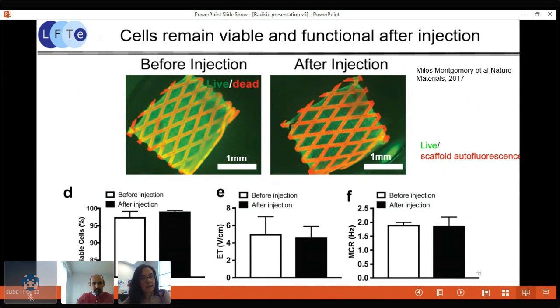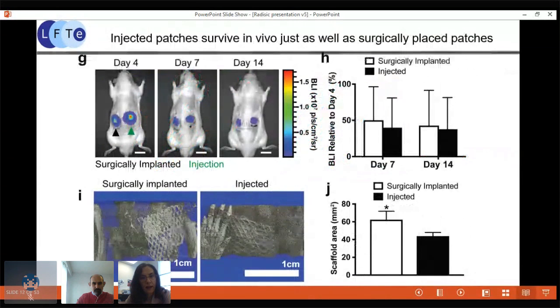In addition to that, the percentage of viable cells really didn't change, and electrical excitability parameters such as excitation threshold and maximum capture rate, which tell how excitable this cardiac tissue is, remained unchanged. This is really important because it tells us that in the short term, the injection does not affect tissue function and tissue properties. It was also important for us to check if the injection and passing of the tissue through a small orifice affects in any way cell death in the longer term.